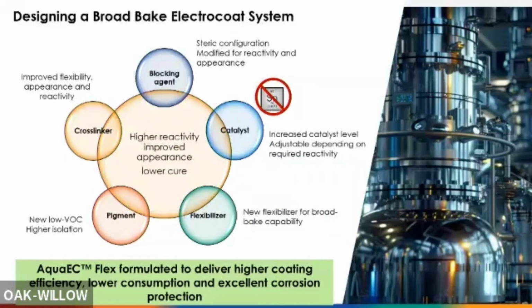In addition to that, we've removed tin. I think a lot of the tin stuff had been around. Tin is a great catalyst, but if we're going to improve sustainability and do some of these other things that we promised the industry we would do, the tin has to come out of the system. In addition to that, we also know that the pigment carries a charge, right? So what we've learned over the years is the pigment charge actually competes with some of the deposition properties. So let's strip away that charge and change the isolation behavior of the pigment as well. All of these things combined increase a very important property for us in the electrocoat world, and that's called wet film resistance. So after I make all of these formulation changes and put my system together, I have basically increased the wet film resistance of this system, right?